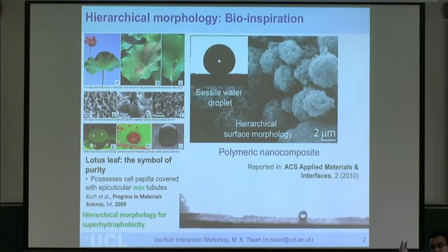So this combination of low surface energy or hydrophobicity and morphology, it's now begun to be understood, is responsible for extreme water repellency of these surfaces. And the beauty with that is if you can imagine some dust lying on this surface, the water droplet, when it comes in contact, beads up like a mercury droplet, and as it rolls off, it cleans the dust away. So that's what leads to the so-called self-cleaning property. And obviously it has some fascinating application potential.